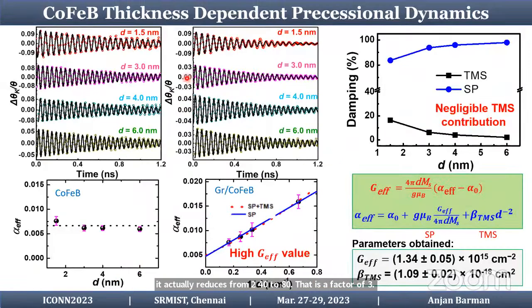In order to understand that, we also studied its damping, because from the modulation of damping, we can find out the spin pumping or the spin transport effect. And we want to see whether the spin transport has an effect on this demagnetization. So we did that. So this is for cobalt iron boron, and this is graphene cobalt iron boron.